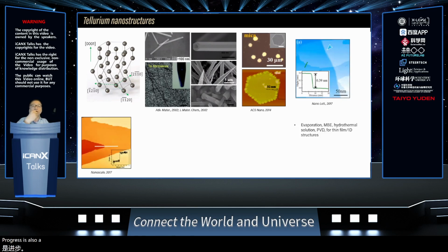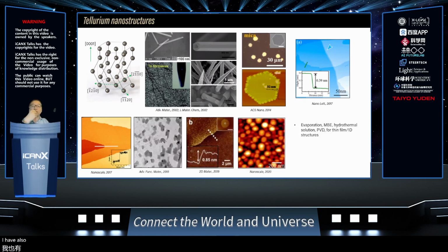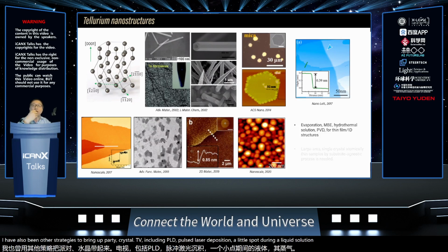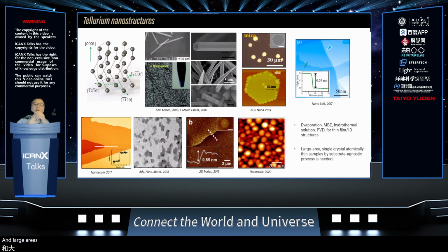Progress has also been made to grow two-dimensional tellurium thin films with the MBE method on graphene substrate. However, these graphene substrates pose challenges for subsequent transport measurements, and they require very complicated transfer methods to detach this monolayer Te film from the substrate. There have also been other strategies to obtain polycrystalline Te film, including PLD, pulsed laser deposition, magnetron sputtering, and liquid exfoliation. Large-area, single-crystal, atomically thin tellurium samples are still missing, especially by using a substrate-agnostic method.